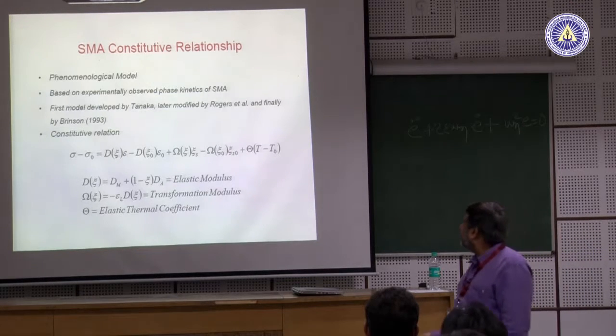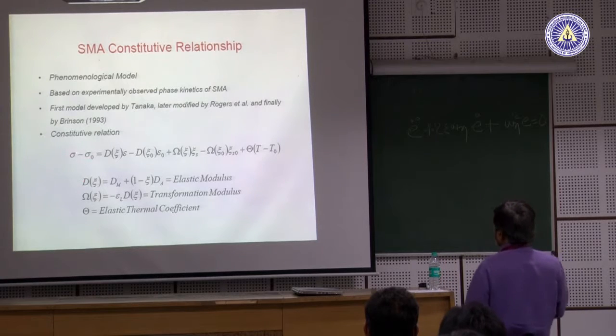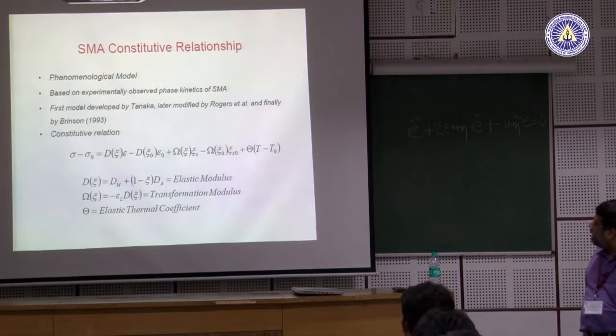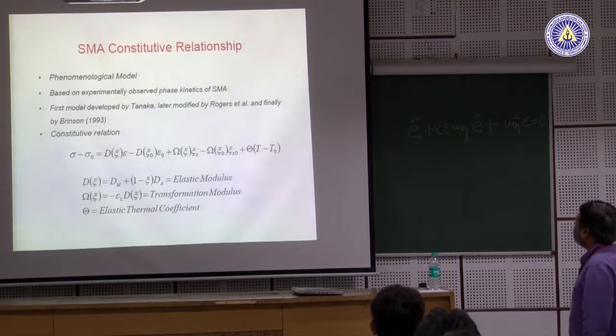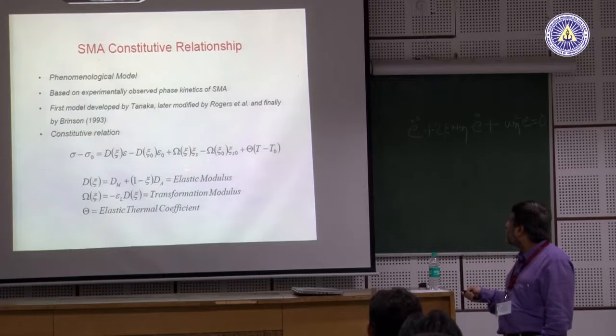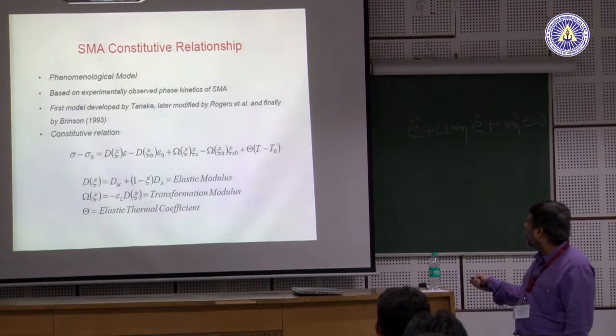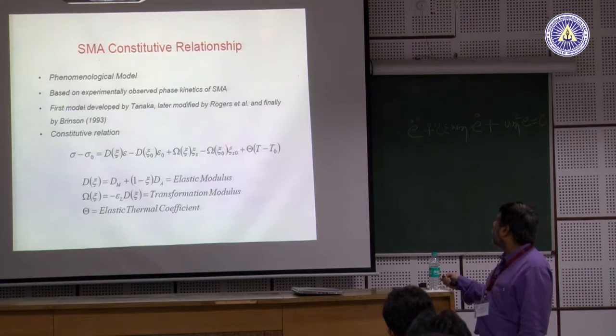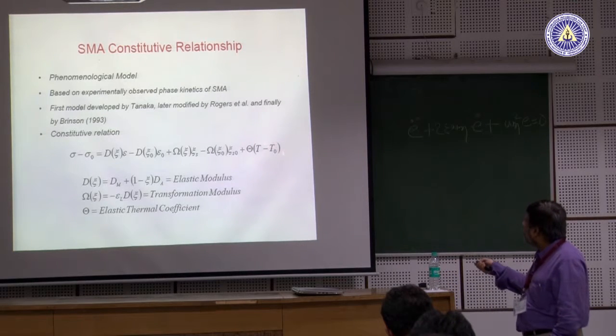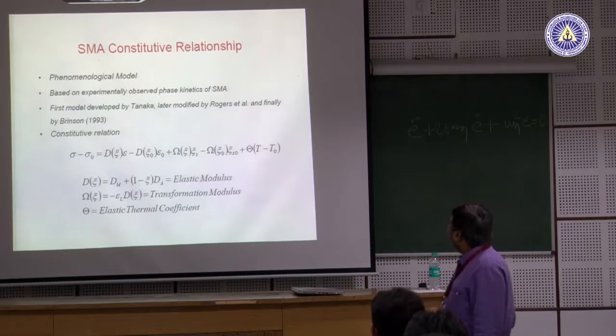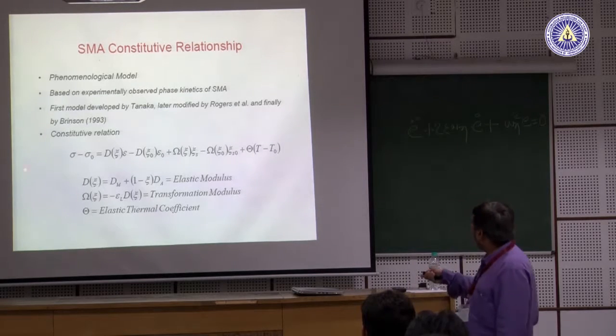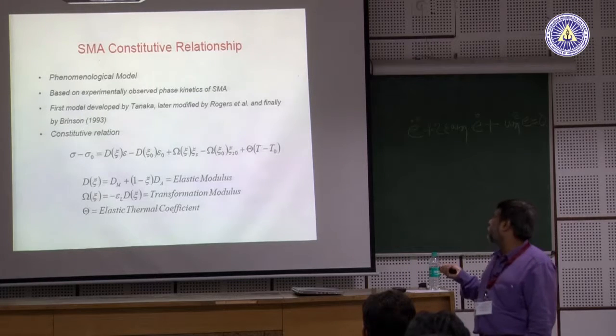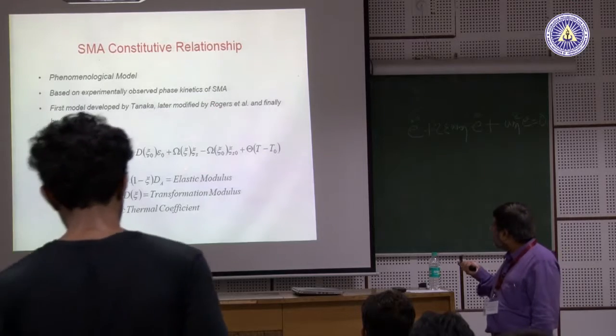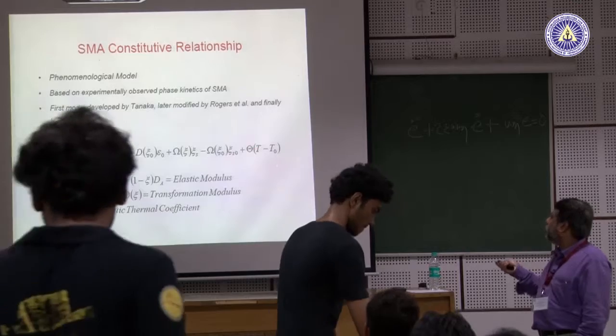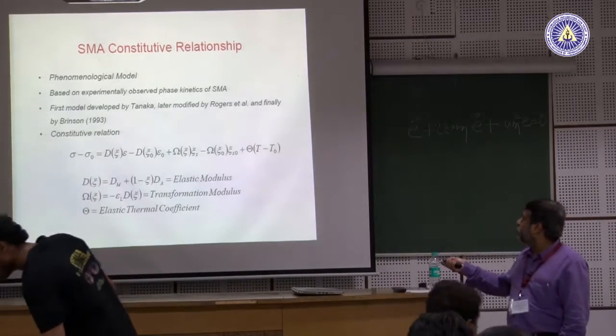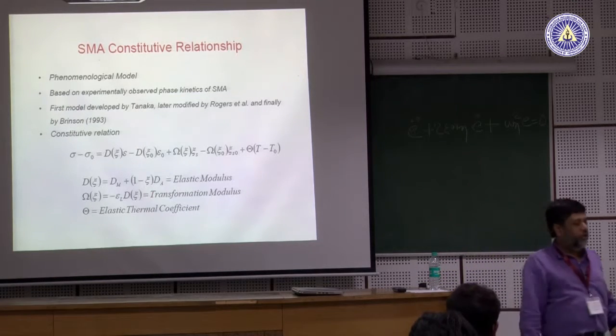Now, talking about strategy is easy, but designing is not at all easy. If you look at the constitutive relationship itself, it is quite complicated. You have the stress on one side, you have the strain, that is the first part with the elastic matrix, then you have the pre-strain, then you have something which is the phase transformation. The zeta s and zeta s0 are all related to how much austenite transformation has happened in the system. And the last part is something related to simple thermal expansion. So, for a shape memory material, in order to know how much force you are going to get every time, you have to solve this puzzle, because you have to know how much strain has happened, how much material got changed to austenite level, and what is the thermal expansion coefficient. Considering all of them together, you will be able to find out what is the stress level or what is the force that you can get from the system.